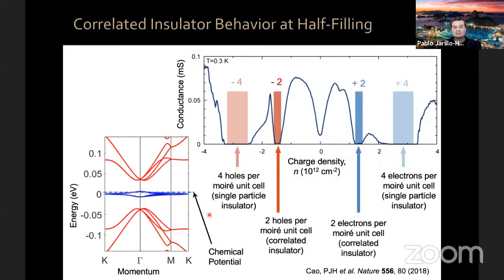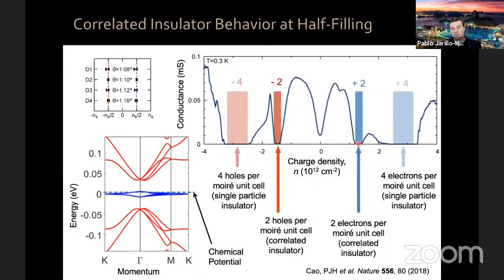If we now shift the chemical potential to the middle of the conduction band, we have 2 electrons per Moiré unit cell in our system. The system should be a metal in single particle physics, but it turns out to be an insulator. So this is also an example of a correlated insulator. And this behavior, which by now we and many people have seen, only occurs when the twist angle between these 2 crystalline graphene sheets is very close to 1.1 degrees, basically between about 1 and 1.2 degrees. That's the angular range for which this correlated insulator physics happens.